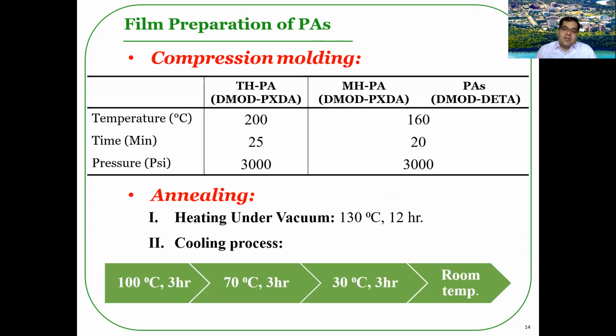The polyamide films were then annealed at 130 degrees centigrade for about 12 hours under vacuum. They were cooled down to room temperature using a stepwise cooling procedure, by reducing the temperature 30 degrees centigrade in each step and letting the temperature remain stable at that temperature for about 3 hours.